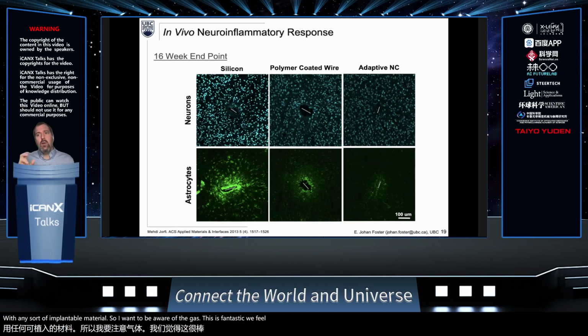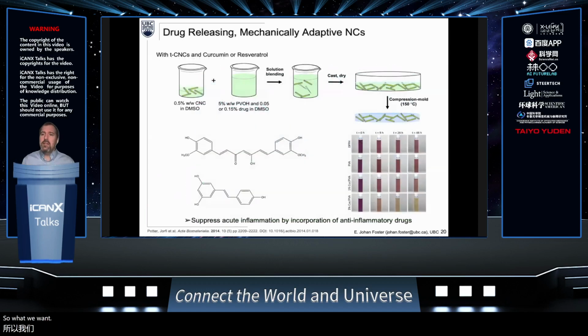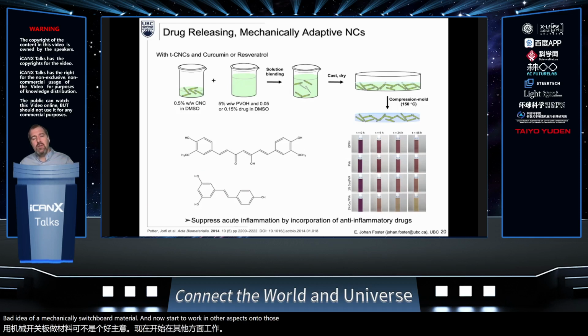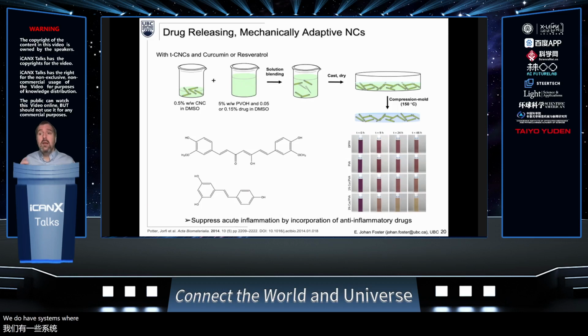Yes, this is fantastic. We feel like we've really solved part of that problem of a material that can adapt to brain tissue and be better, but it's not perfect. Okay. So what we want to be able to do is deal with that inflammation. So we're going to combine that idea of a mechanically switchable material and now start to work in other aspects onto those cellulose nanocrystals, onto that rod-shaped filler, to be able to deal with other problems, in this case with implantation. So we made a first generation of this material very simply by mixing in anti-inflammatory drugs into our adaptive nanocomposite. So combining those drugs with the CNCs, they adhere to the CNCs, or they don't chemically bond to the CNCs in this case, although we do have systems where we do that now.